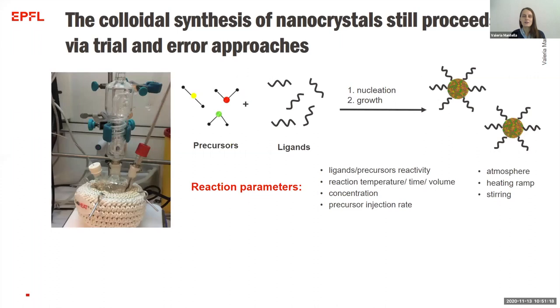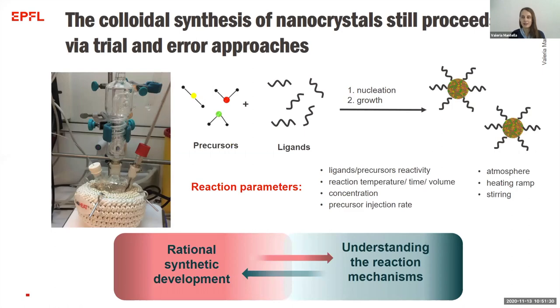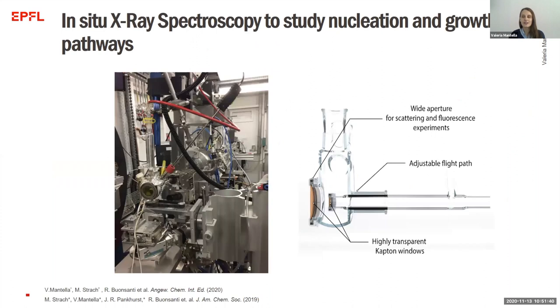As Professor Buonsanti already told you, the colloidal synthesis of nanocrystals still proceeds via trial and error approaches. So we really need to understand the reaction mechanism underlying nanocrystal formation in order to move towards a more rational synthetic design. Our strategy here is to directly monitor these chemical transformations by in situ X-ray spectroscopy using a custom-made reaction cell that mimics the typical colloidal reaction flask. So we can exactly reproduce the typical laboratory environment while acquiring X-ray absorption and scattering data up to 300 degrees.